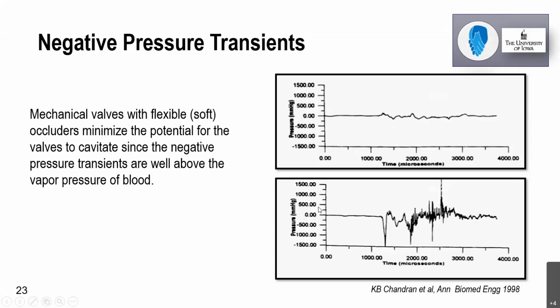And we did a series of studies at the University of Iowa on this, and we found that the one on the top, which depicts the soft disk valve, the negative pressure formation is extremely low. And because of this, the propensity for formation of cavitation bubbles is very less. While in the case of hard disk material,